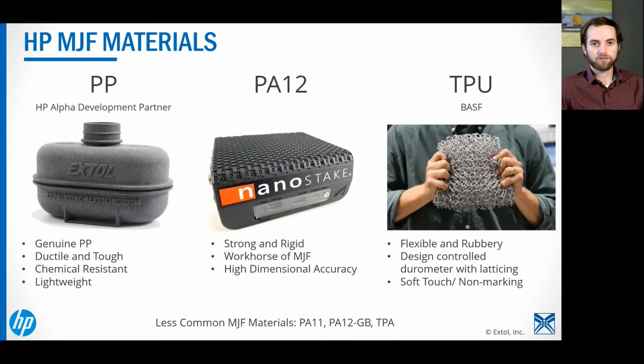Extol offers 3 different materials: polypropylene, PA12, and TPU. Polypropylene is a newer material for which we were the alpha development partner. Being able to weld multi-jet fusion polypro printed parts to a wide range of polypropylene or TPO family of injection molded parts unlocks more functional prototyping opportunities. PA12 is a strong rigid material with high dimensional accuracy, and TPU is a flexible elastomer that is great for soft touch and non-marking applications.